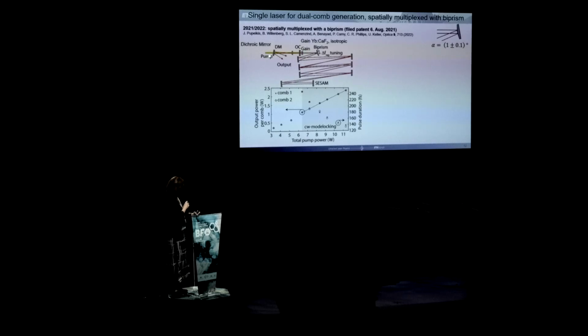So you have basically a gain material here. It's a ytterbium-doped solid-state laser, an output coupler, and you pump 2 spots here separated in the gain, and because you replace a flat mirror here by this biprism, you then have also 2 spots on the SESAM, and you have different path lengths. Both of the combs are nicely, stably mode-locked, soliton mode-locked. Next slide. And you get your nice spectral overlap, perfect, because of course it's ytterbium doped equal everywhere inside the crystal.